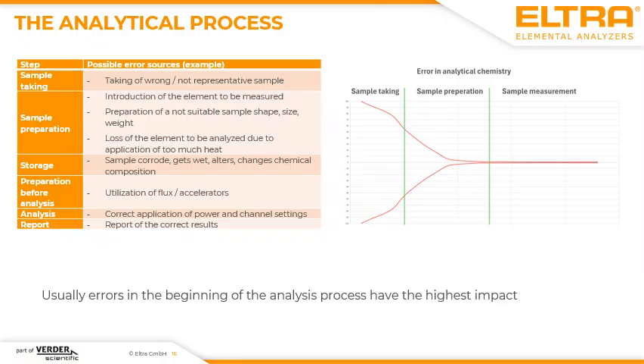It's also the effect, for example, when you prepare the sample with too much heat, then the result is already falsified significantly. And especially in case of oxygen analysis, you will get in big trouble when you store the sample too long, because you could have a lot of oxidation effects.